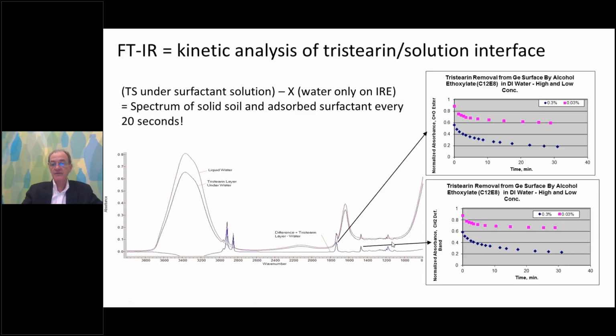And we plot several of them to make sure we get the same trend. And what we see here is that for both surfactant concentrations, high and low, initially there's a significant removal of the tristearin, but at some point, at a little bit longer times, that removal slows and eventually stalls.